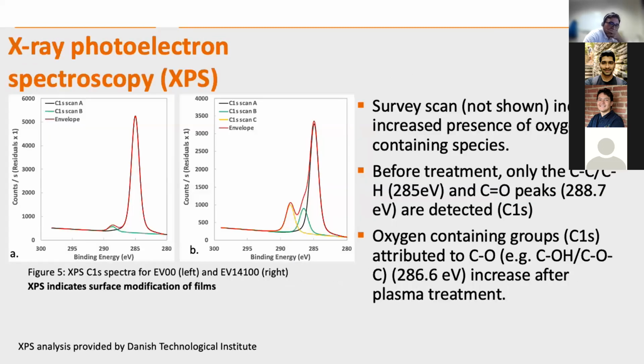Now I would like to talk a bit more about the XPS, or X-ray photoelectron spectroscopy spectra. Figure 5, A and B shows XPS spectra of an untreated and a treated sample. The region corresponding to 286 electron volts on the x-axis represents the amount of oxygen containing groups on the surface. As we can see, on the untreated sample there is no peak observed at 286 electron volts, whereas we can see a giant peak at 286 electron volts for a treated sample.